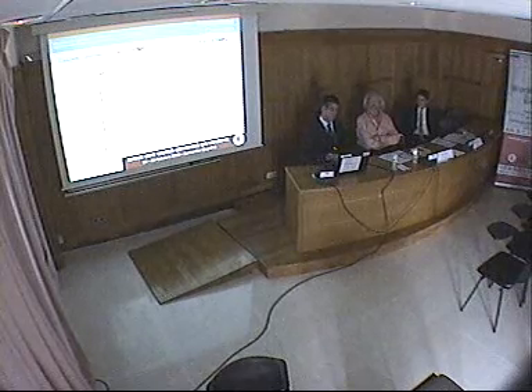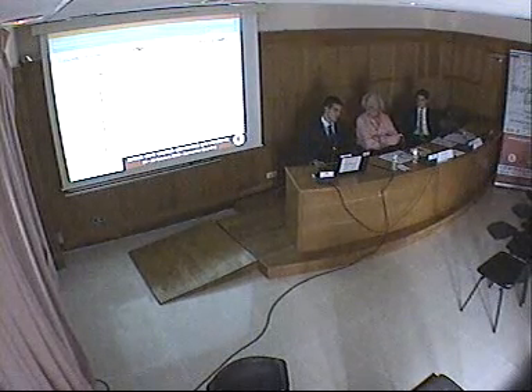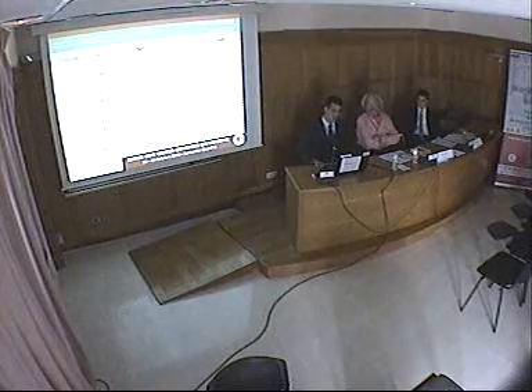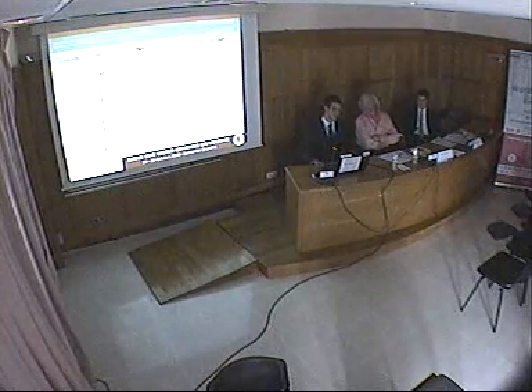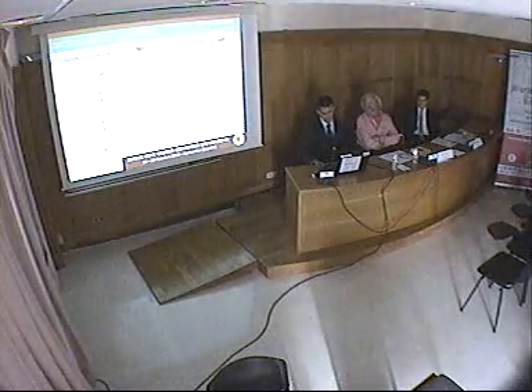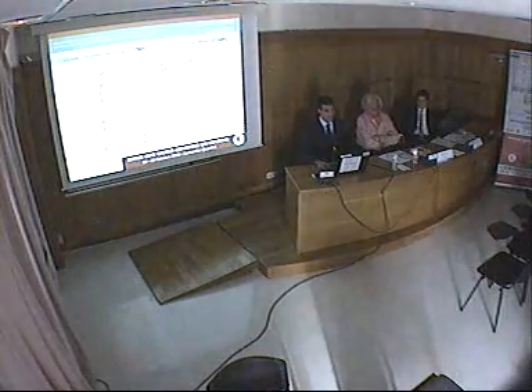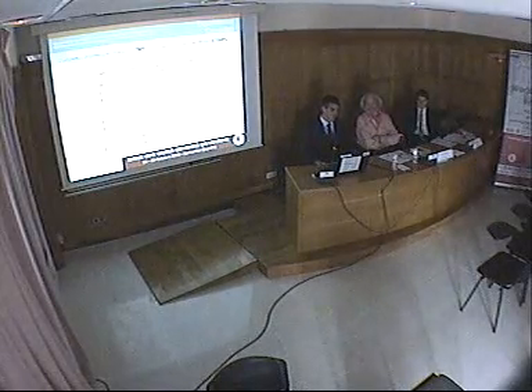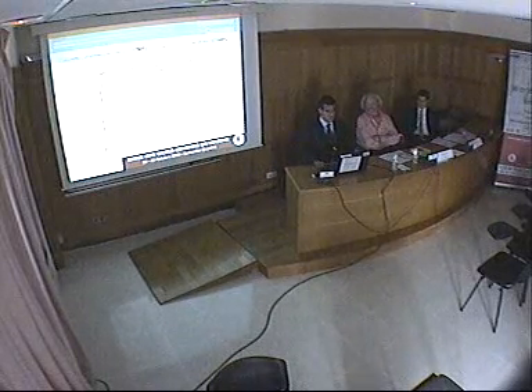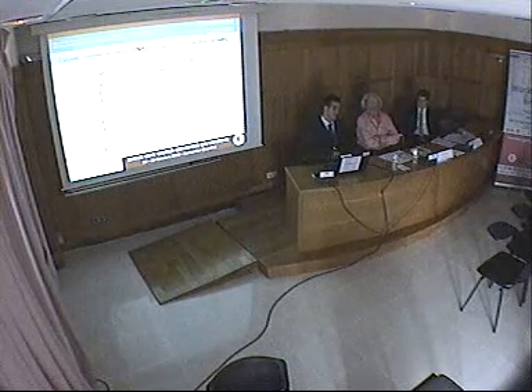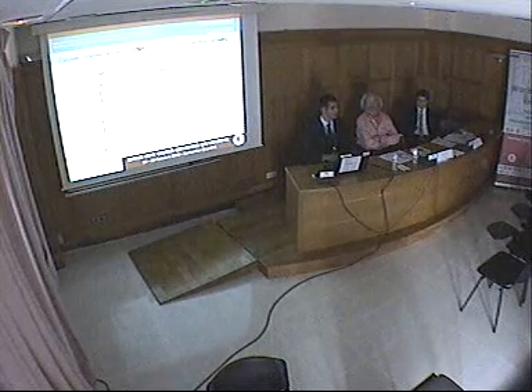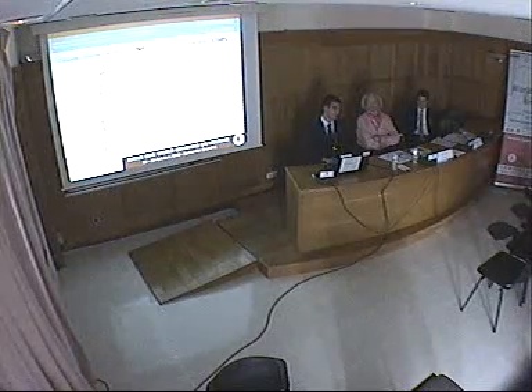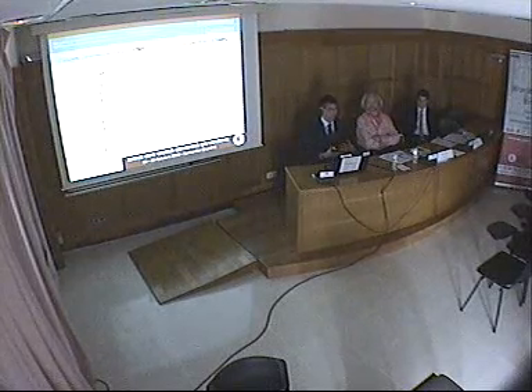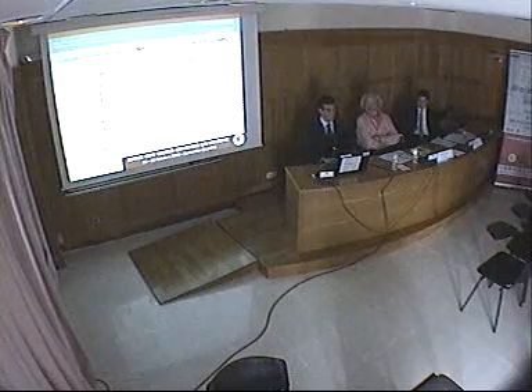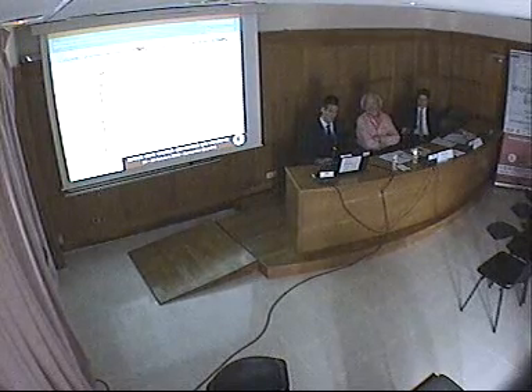And in basalt, it's divided in two stages. The first one is with no anchors. And in the second, we are going to see now the failure mechanisms. So in some situations, we use anchors in the ends of the strengthening system. And as you can see, we play with the number of layers, 2 of basalt to see the difference, and 3 of low density steel, because we want to see the same amount of medium density, but in this case the shape is different. So the penetration of the mortar in the low density is better than in the medium. So we wanted to check that.